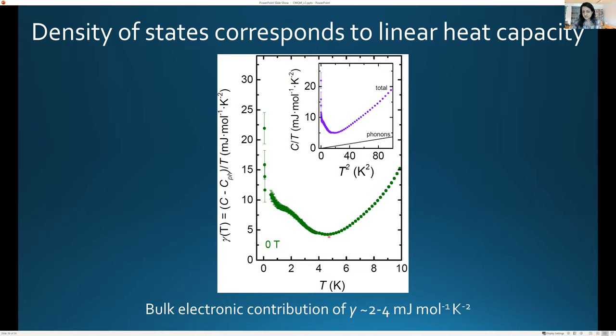We don't know where this comes from. Maybe it's from many body effects, which basically means we don't know where it comes from. So we're revisiting the same unexplained finite linear heat capacity that was seen several years ago. But now we're saying, well, it's possible that this finite linear heat capacity could be consistent with the density of states that we're seeing corresponding to the Fermi surfaces.